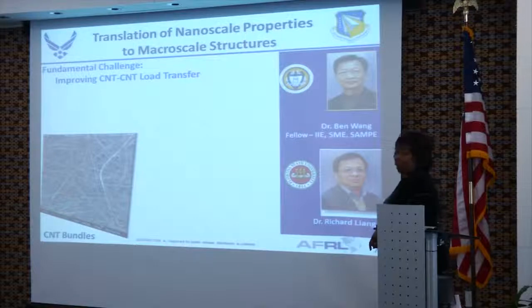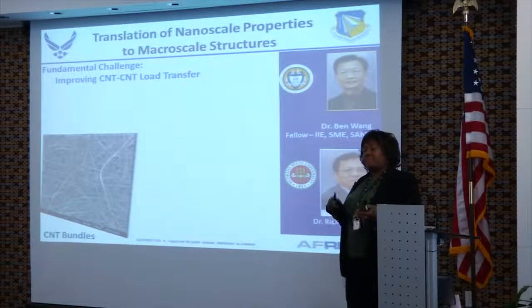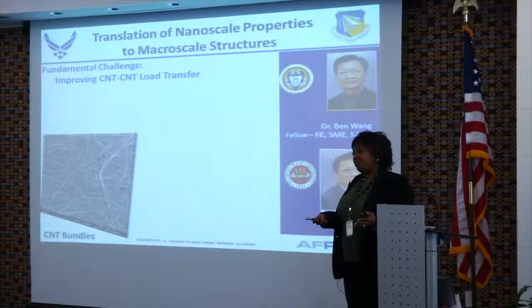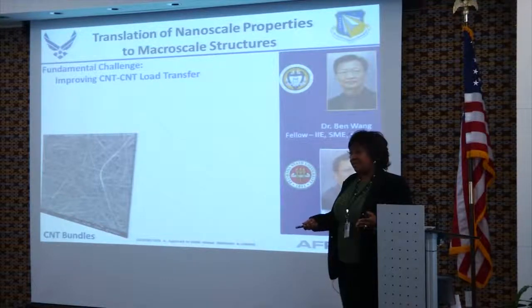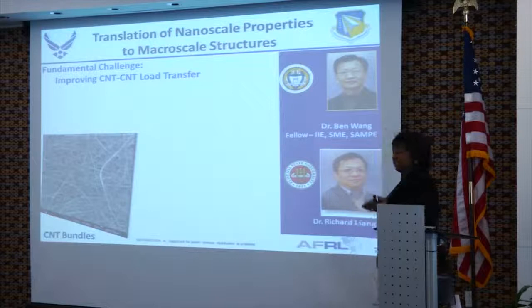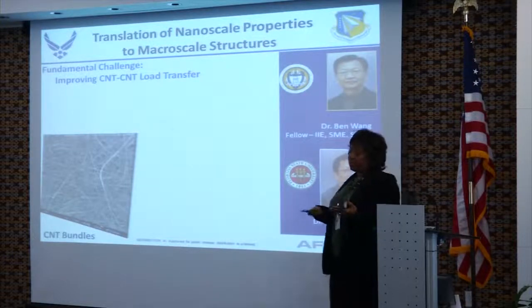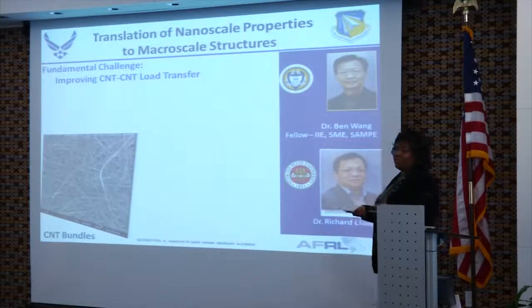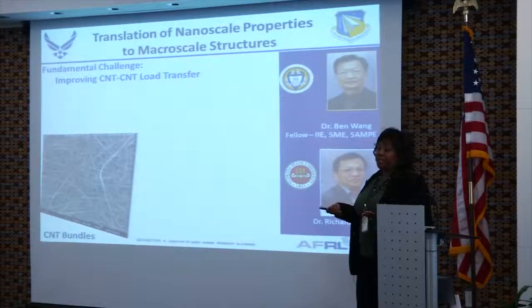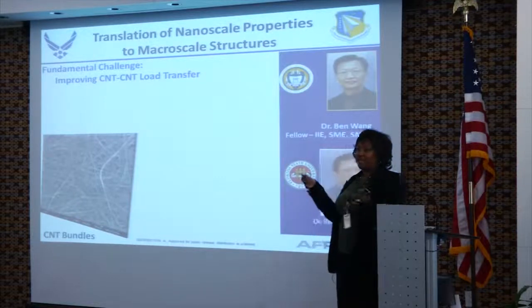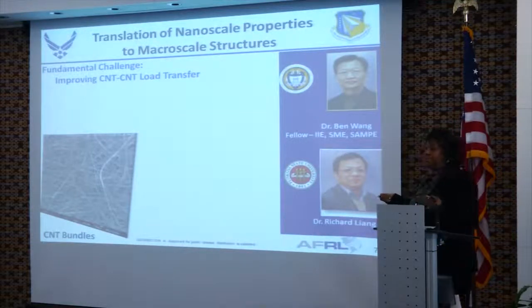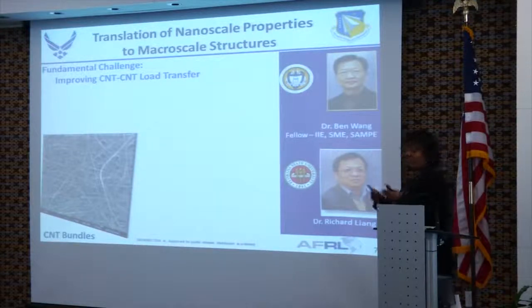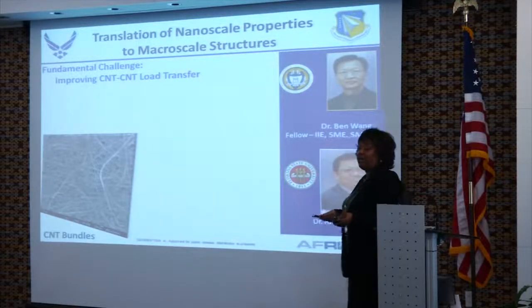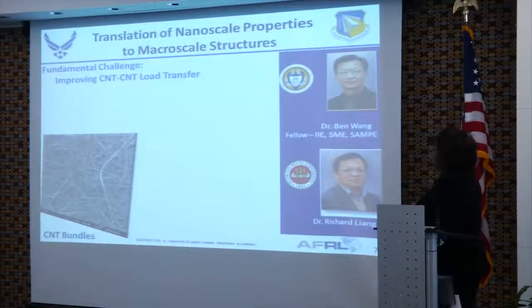Their approach is twofold. They're looking first at mechanical consolidation issues, and then secondly at chemical consolidation issues to try to understand this. If you look at the materials that have been made with nanotubes incorporated, nanocomposites, what you'll see is that the primary failure mechanism is nanotube pullout. If you examine these under SEM, you see that that's the failure mechanism that is most commonly encountered. And so that tells you that there's a coupling issue going on, that you're not coupling that load into the tubes.